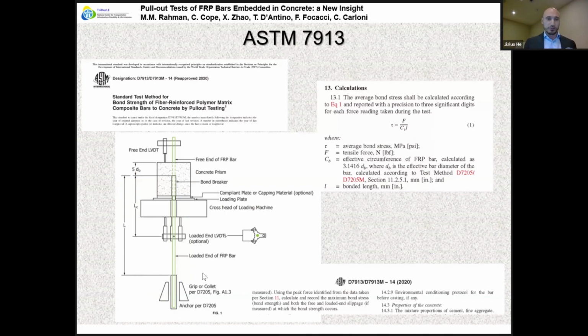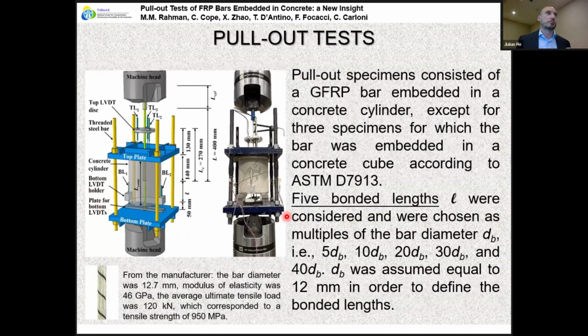If you're not familiar with the method, it's a very simple method. You take a block of concrete, you embed the FRP bar with an extended part outside at the free end, and you pull at the loaded end, and there is a bond breaker to avoid the cone effect. The average tau is simply calculated as the peak force divided by the lateral bonded area of the bar. So we try to see a little bit more about this bond.